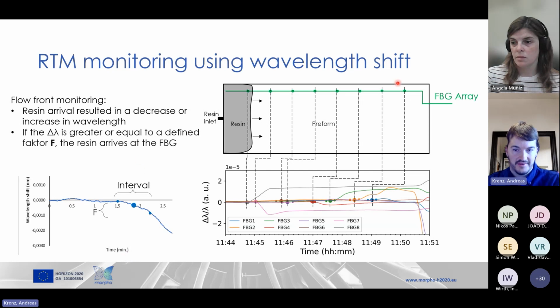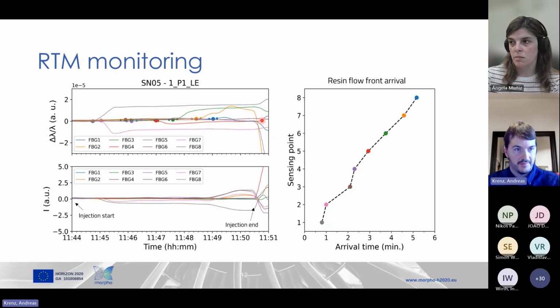And this figure shows the passage of the resin going through the FOD panel from the left to the right and passes all the FBGs in this array. And here's the associated FBG signal, which shows an increase or decrease of the signal. And using this FBG-based data, it is possible to have this RTM process monitoring. Here's the same wavelength shift graph as previously shown, and also the intensity shift for the same time.